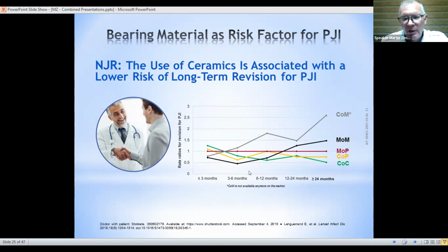If you concentrate now on the 2 years results, you can see that compared to metal on polyethylene, which served as a reference, by using metal on metal or ceramic on metal, which actually does not exist anymore on the market, you have an increased risk of revision due to PJI. In contrast, by using ceramic on ceramic as well as ceramic on polyethylene, you have a lower risk of revision due to periprosthetic joint infection.